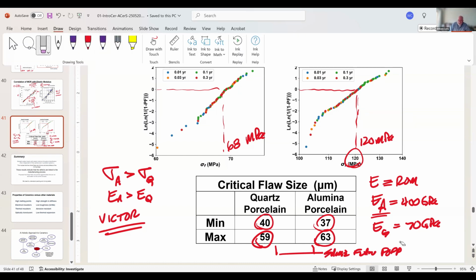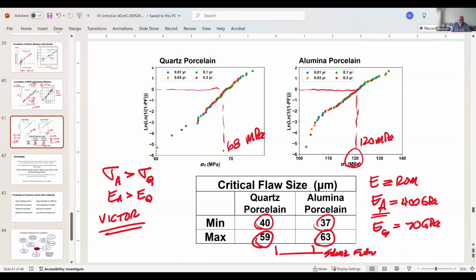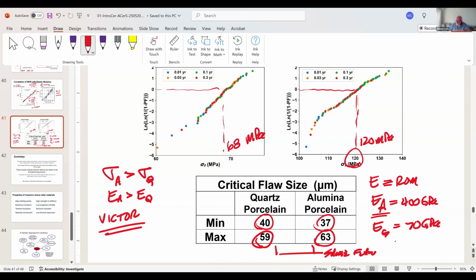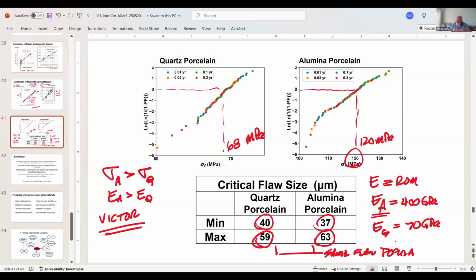Okay, these two samples have exactly the same flaw population. What does that mean? Okay, same flaw population. All right, this means that they're processed in the same factory. That factory has an intrinsic, if you will, flaw population. If I go to another manufacturer, I may find that their flaw population could be smaller or larger than this, right? But the fact is that I have a much stronger alumina porcelain here, but it has the same flaw population. So that improvement in strength is only due to the elastic modulus,